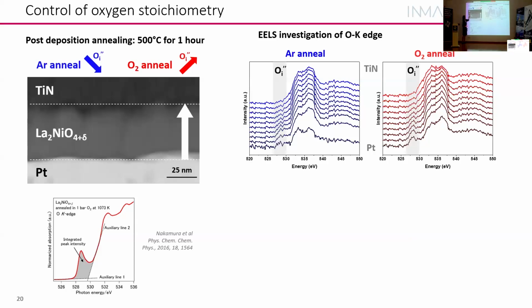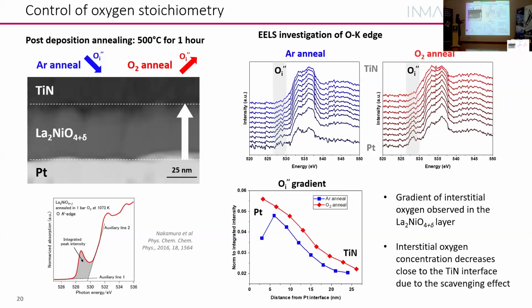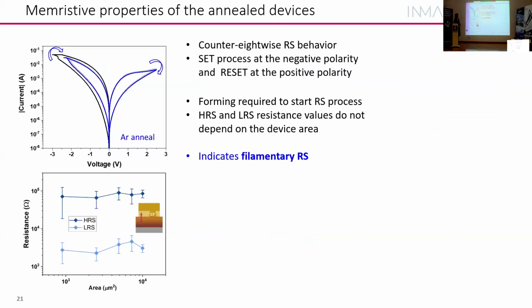So there's oxygen, and this we proved by EELS with César Magén from INMA, that the oxygen concentration changes from the bottom to the top electrode. And we can see this by the appearance of this pre-peak and the lower intensity at the top compared to the bottom. So we have a gradient in oxygen concentration through our film. And that is what is shown here, where we plotted the oxygen gradient as a function of the distance.